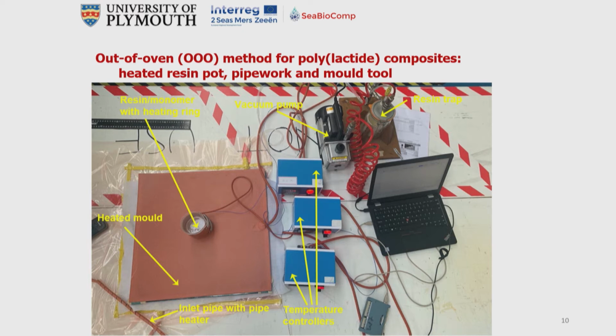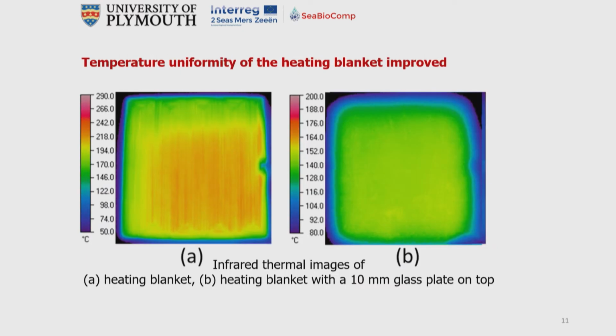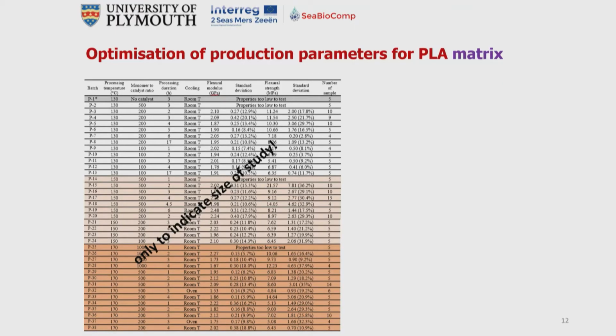I won't dwell on this slide. One of the issues we had was temperature uniformity across the mold tool. So we found that using a glass plate between the heaters and the mold tool spread the heat more uniformly and gave us flow that was closer to what we expected. And then we did a pretty comprehensive study. I'm not expecting you to read the numbers off this slide, with a variety of different parameters to try and identify how we might produce the PLA.